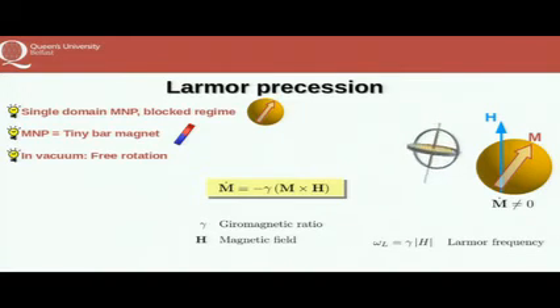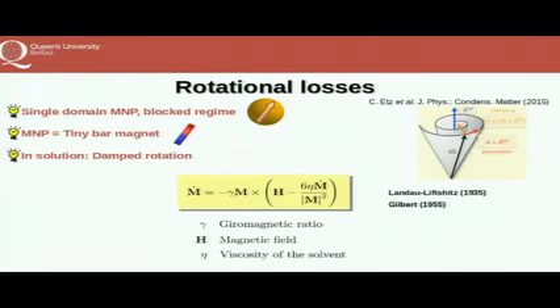But we know that in order to minimize the energy, the external magnetic field and the magnetization should align. So there is a missing term in our equation of motion, and this term accounts for the dissipation and has been derived in different forms by different physicists. This equation comes under the name of Landau-Lifshitz-Gilbert equation. We have the same terms that you saw before, accounting for the free precession, and then a new term which depends, thankfully, on the viscosity and on the time derivative of magnetization. So it's not as good as an equation of motion because it's still implicit. We have the time derivative here and there.